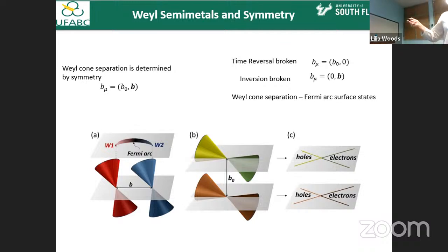Now, if the displacement of the cones is in momentum space, right here, we have an additional non-trivial property that comes from Fermi arcs on the surface. But if the displacement of the cones is in energy space, nothing like that. This is controlled by a time reversal symmetry that is being broken or an inversion symmetry that is being broken. Now, if the cones are tilted too much, there is also another thing, which is that the density of states of the electrons and holes now is significant.